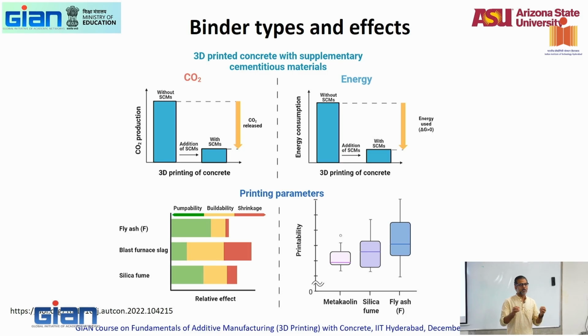You will get, because of its finer particle sizes, the ability to get it in different particle sizes that you want, and the fact that it really doesn't interfere much with cement hydration. It'll stay as a filler, it'll do some fine filler effect. You can start to play around with particles. So really the idea is using binders. Now I've put in metakaolin also.